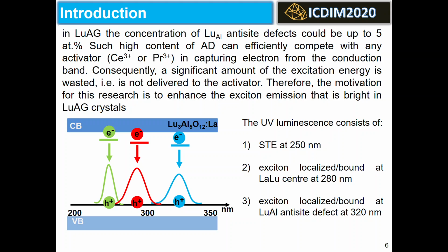In lanthanum-doped LuAG, we can observe three types of exciton luminescence. At low temperature, exclusively self-trapped exciton luminescence at 250 nanometers. At room temperature, there arises luminescence of excitons localized and bound at lanthanum-lutetium centers at 280 nanometers and luminescence of excitons localized and bound at lutetium-aluminum antisite defects.